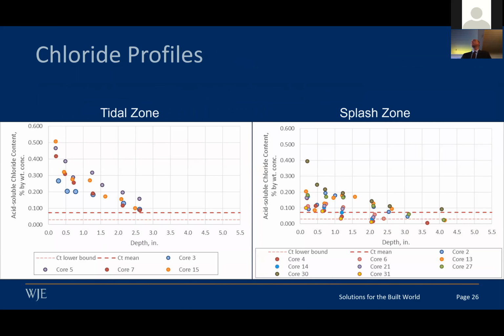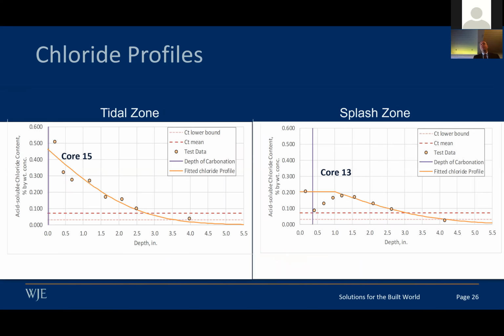So this is just some of the data that we collected while we were doing this assessment. These are the chloride profiles for different cores with depth. And you can see that in the tidal zone, you're getting high values right at the surface, which is expected because you get the water and splashing from the chlorides. And then as you go deeper, the concentration is going down. And so we fit curves to represent that so that we could use it for our models. Just because it's a probabilistic approach, it needs an actual number as opposed to a bunch of data points. So these are some of the curves that we used.